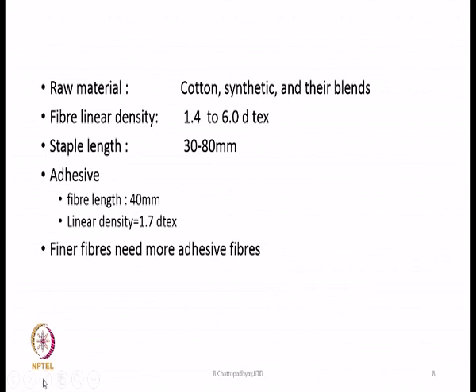As I said, we can have either synthetic fibers or cotton or blends, viscose rayon we can use. We can use lyocell fiber also, synthetics we can use polyester, acrylic, whatever fibers we require we can use. The linear density of the fibers could be anywhere between 1.4 to 6 decitex. Staple length could be 30 to 80 mm. Generally, that means fiber should be long, and the length of the adhesive fiber, that is PVA, is typically 40 mm and its linear density is close to 1.7 decitex. Finer the fibers, we need more adhesive fibers.